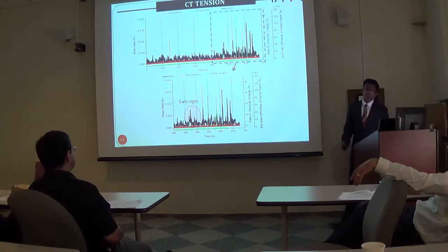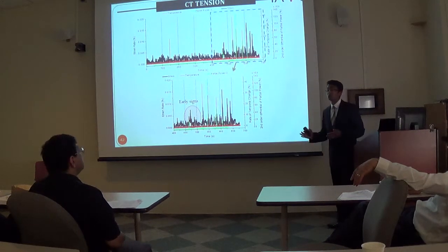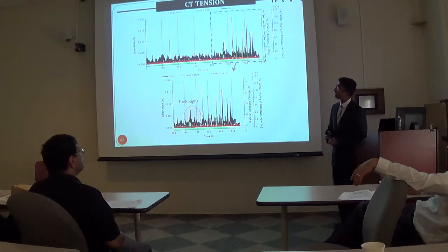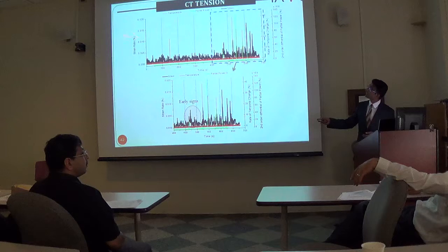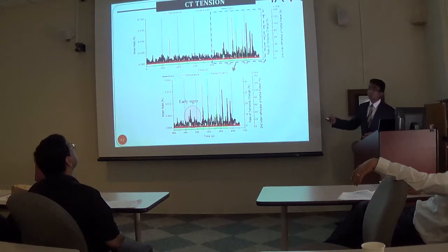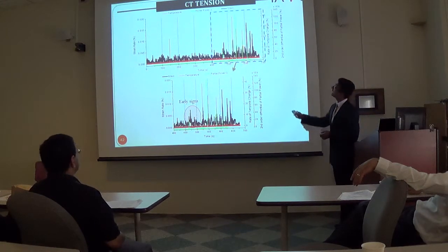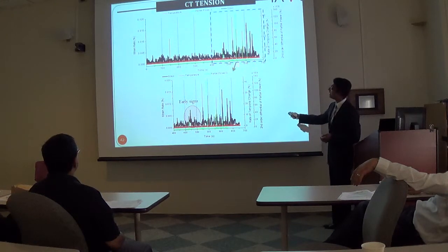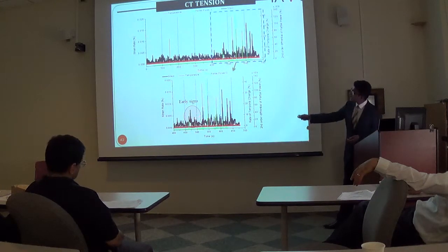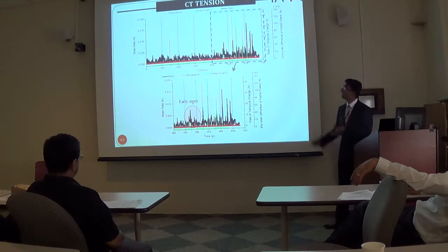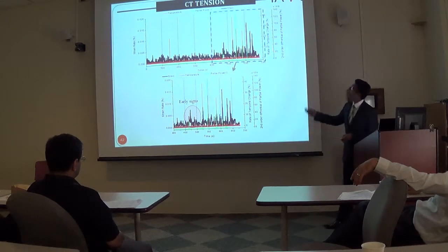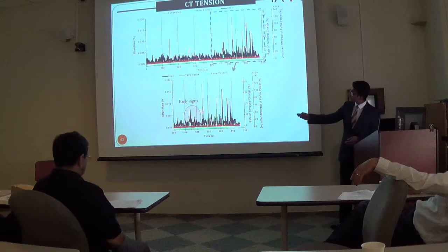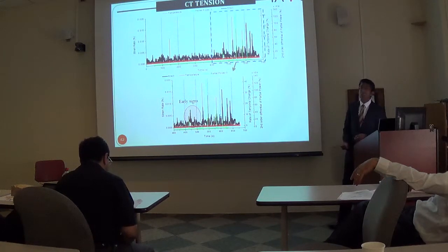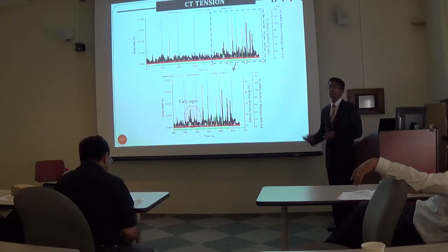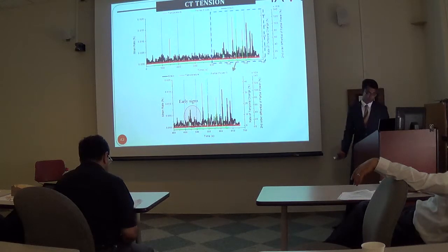the material. Now, in order to confirm that the partial power analysis was sensitive to the crack initiation in the material, the partial power analysis was correlated with independent features that were extracted from the DIC, such as the strain, and the temperature that was extracted from infrared thermography. And it can be seen right at the final stages of the failure. You can see how the partial power analysis is coincident exactly with the full field strain values and the temperature change. And much prior to actually visually seeing the crack initiation, you can see early signs of damage using the acoustic emission partial power analysis.